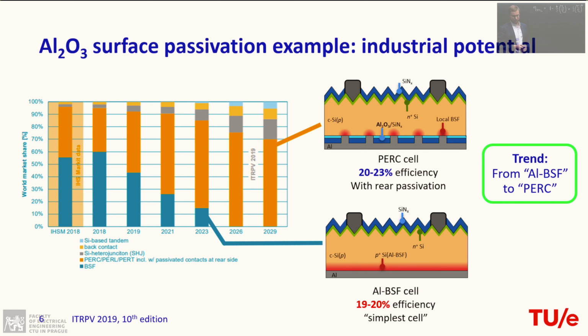So the trend is that we go from this bottom structure towards the PERC cell, which is to a large extent actually enabled by aluminum oxide, which we have also over here on the rear side in combination with silicon nitride.